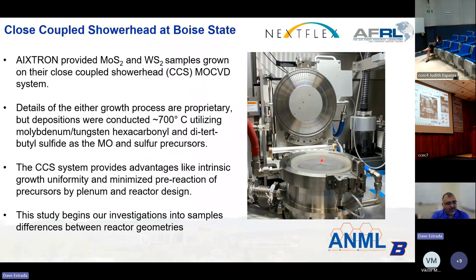We've also, here at Boise State, recently acquired an Aixtron close-coupled showerhead system for MOCVD growth of these films. And the advantage here is that you can see, if you look closely, this array of holes in the top of the showerhead. So we get vertical flow of our gases instead of horizontal. And the gases are perpendicular to the wafer surface. So we could take a 4-hour growth from horizontal reactor geometries and do the same growth in 10 minutes on multiple wafers, which are rotating with the showerhead system, right? And so it's a much more industry scalable technology than the horizontal quartz tube.